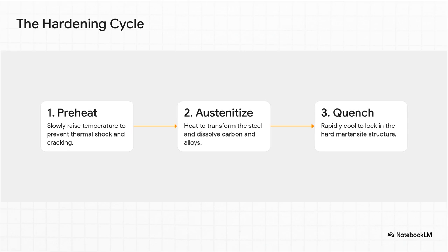First, you have the preheat. This is a gentle warm-up to stop the steel from cracking from thermal shock. Next, you austenitize, which is when we heat it up to create that carbon-soaking sponge we talked about. And for the grand finale, the quench.